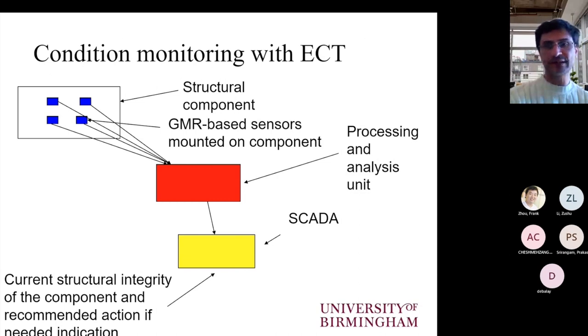Condition monitoring is also feasible with eddy current testing. We can use conventional eddy current probes, or we can use GMR-based probes, which are mounted on the component on a permanent basis in an area of interest, such as a riveted area, for example, a riveted component. And then we can monitor these coils or GMRs continuously to assess any crack initiation and crack propagation. This can be fed to a processing and analysis unit, which is local, before being relayed to a supervisory control and data acquisition system where the data are stored and analyzed all together from a set of nodes that we have used to instrument potentially different components and not just a single one.